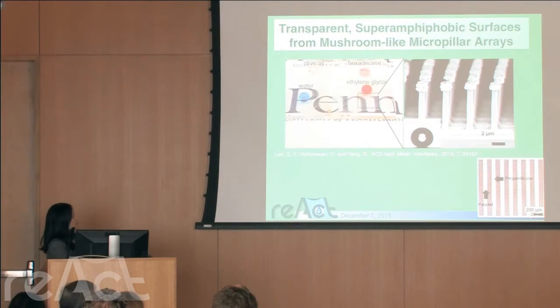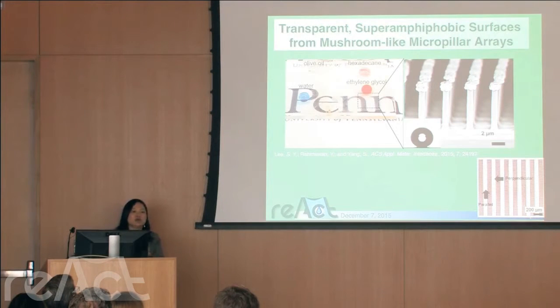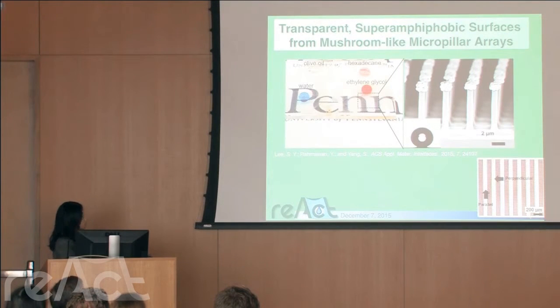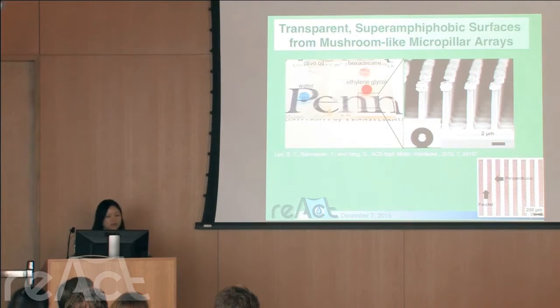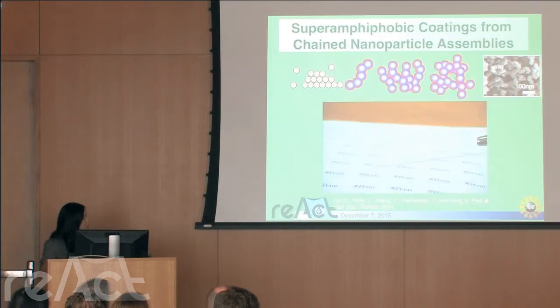And so we show here the nanoparticles act as a mushroom surface. So we can introduce superhydrophobicity, also superoleophobicity. All right, so antifouling is not just anti-water, it's also very important to be anti-oil, against low surface energy contaminants. And further, if we change the spacing between these pillars, we can make them transparent. We can also pattern this, so you have this wetting anisotropy. You can guide the water flowing. All right.